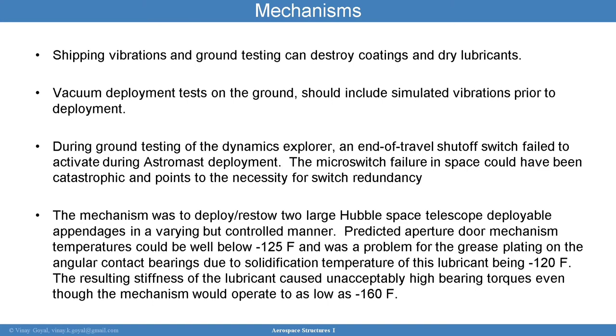I want to also point out that shipping vibrations and ground testing can destroy coatings and dry lubricants. Vacuum deployment tests on the ground should consider simulated vibrations prior to deployment. And during ground testing of the Dynamic Explorer, an end of travel shutoff switch failed to activate during the Astromast deployment. So we had an issue there with the microswitch, and the failure in space could have been catastrophic, and it points to the necessity of having redundancies.